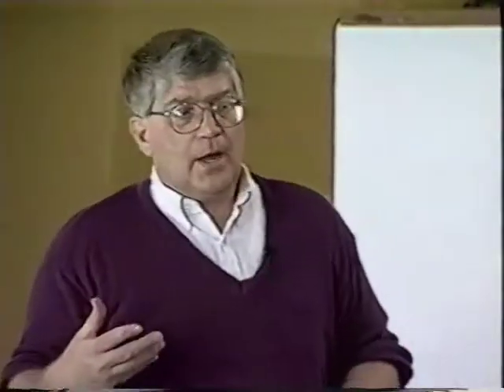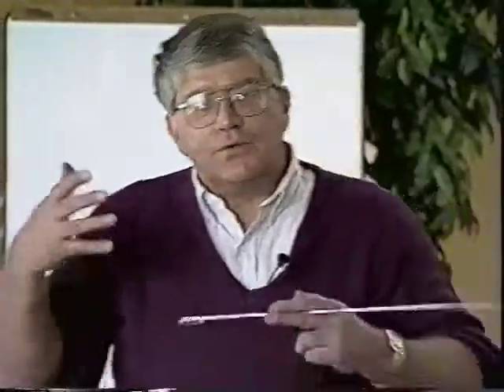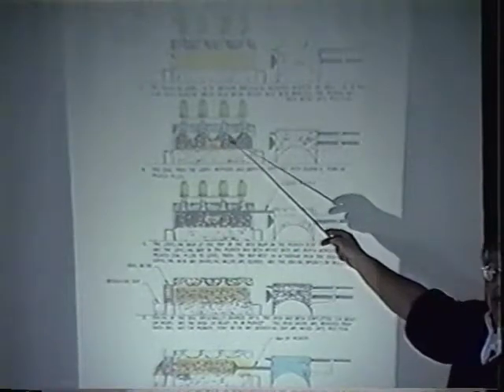Okay, now this is the coking process. We have the Larry car, and we have an empty oven. Volume about 1,390 cubic feet. We'll take 34 tons of coal, and we put it into the oven. Now we put it in a certain way basically for pollution control. We stage charge it. We don't put all the coal in at once. We put the 2 outside hoppers in, and then we put the lids back on, then we put the second hopper in, put the lid on, then we put the third hopper in. That way we can control the emissions.